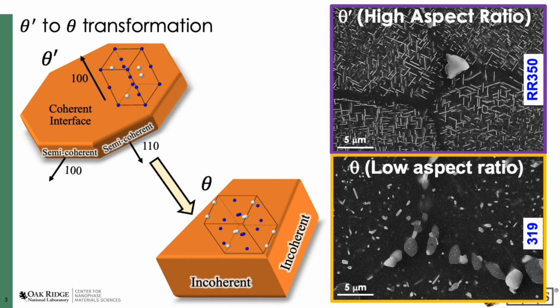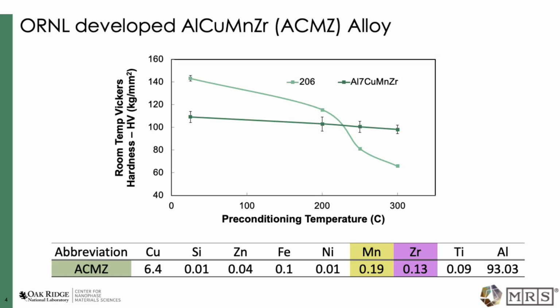Unfortunately, the theta prime precipitate is metastable and eventually transforms into theta, which coarsens rapidly and decreases the hardness of the material. Oak Ridge National Laboratory has recently developed an aluminum copper manganese zirconium alloy deemed ACMZ. This alloy retains its hardness all the way up to 350 degrees C after a 200-hour exposure. The important and critical solute additions are manganese and zirconium.